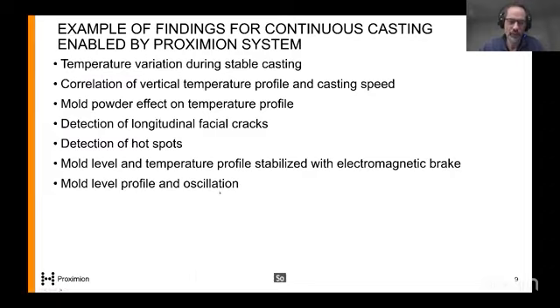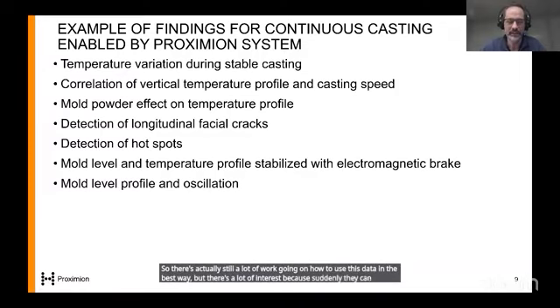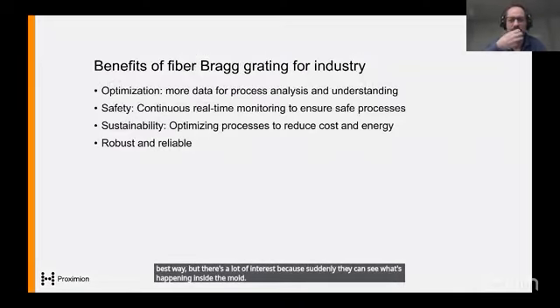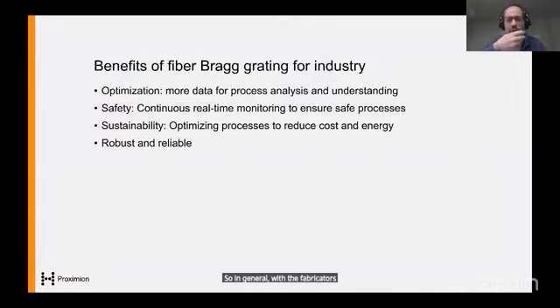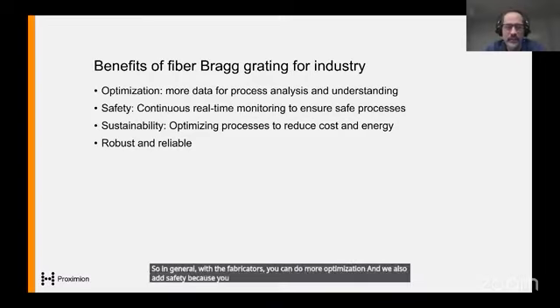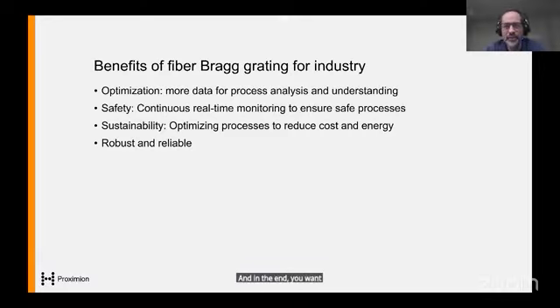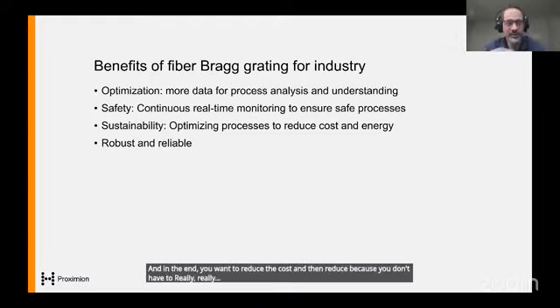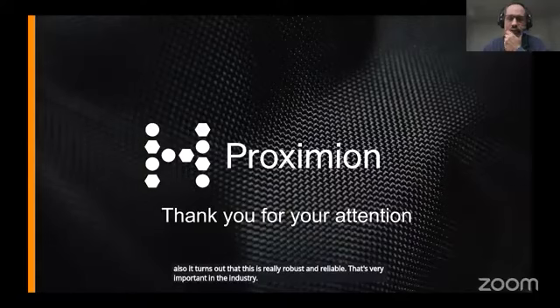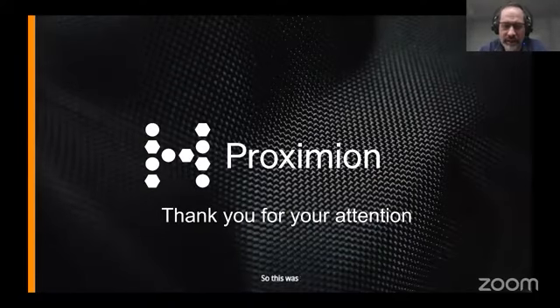There's still a lot of work going on on how to use this data in the best way, but there's a lot of interest, because suddenly they can see what's happening inside the mold. So in general, with fiber Bragg gratings, you can do more optimization, and we also add safety, because you can detect these breakouts. In the end, you want to reduce cost and energy use, because you don't have to redo, remelt, when it really goes bad. It also turns out that this is really robust and reliable, which is very important in the industry. So this was all from me, and thank you for your attention.